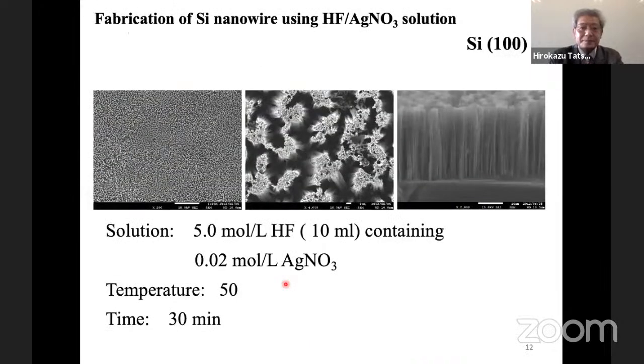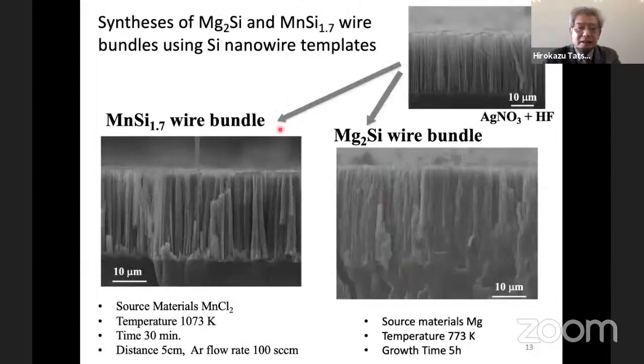So using this technique, fabrication of silicide nanowire bundles can be done. This is a silicon nanowire array, made using simple chemical reactions. After making such structures, these silicide wire bundles can be formed by thermal annealing with manganese chloride materials and magnesium vapor pressure in the vapors. So we try these wire bundles for thermoelectric generators in the future.